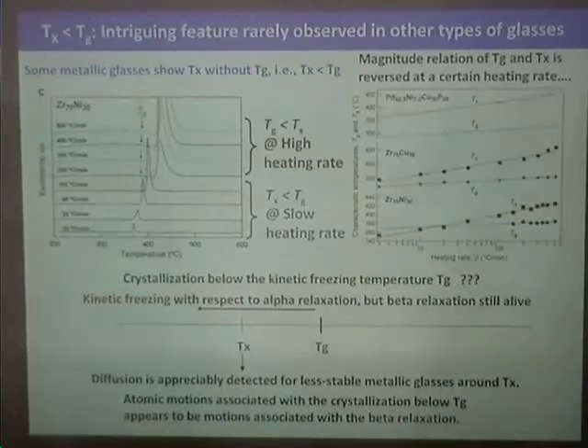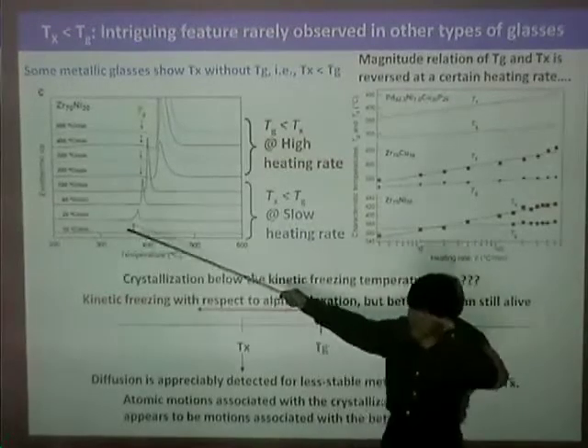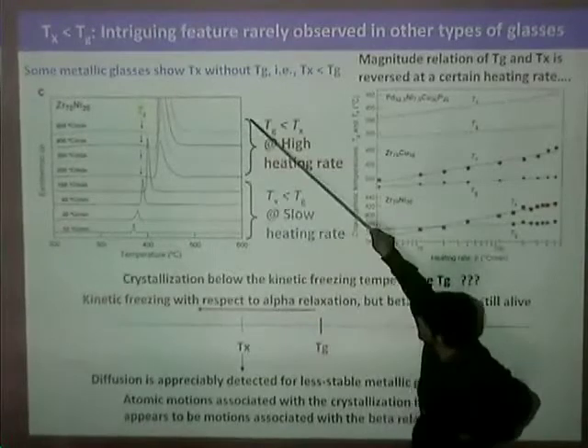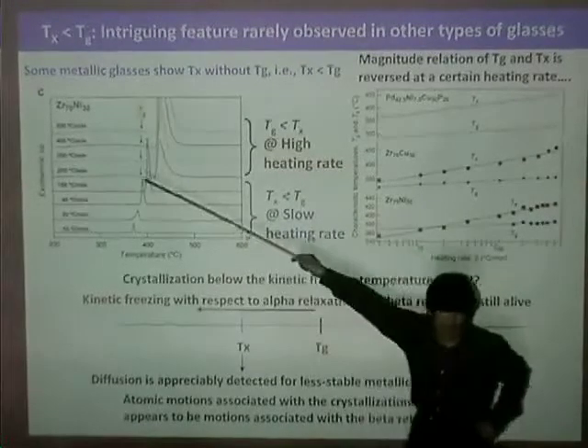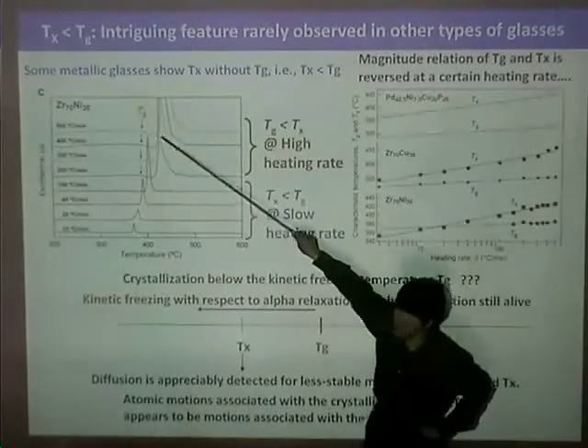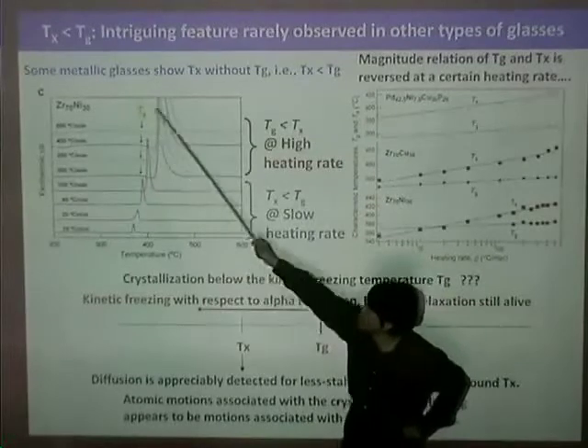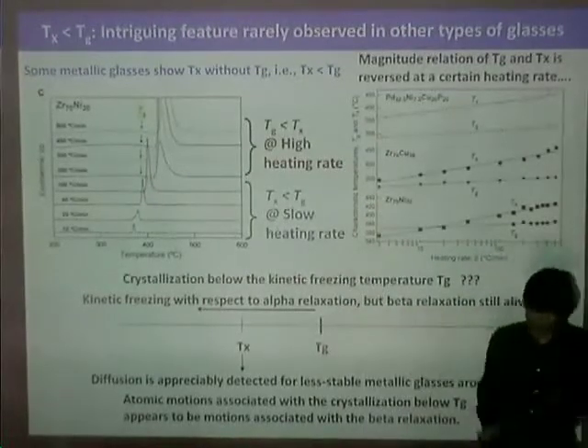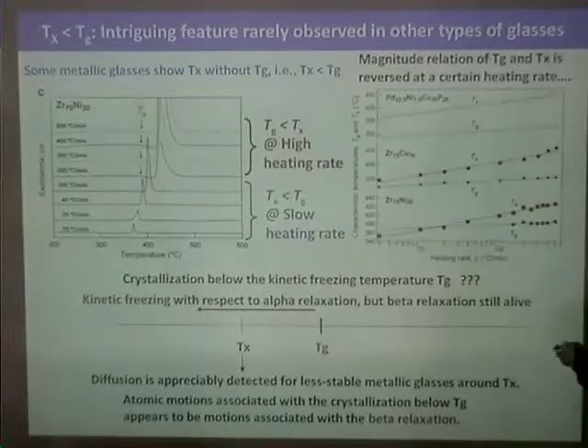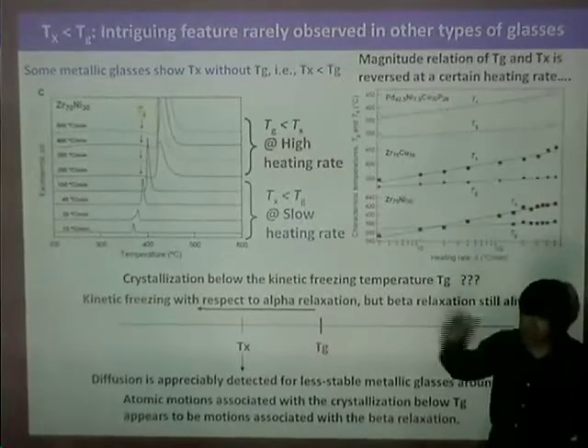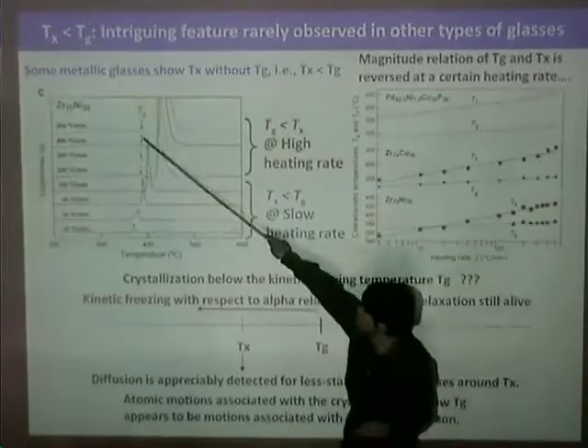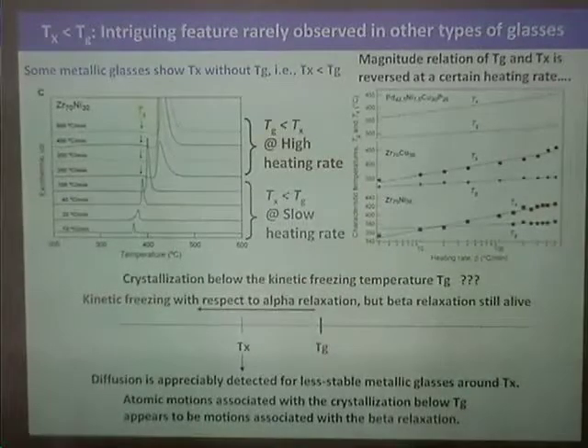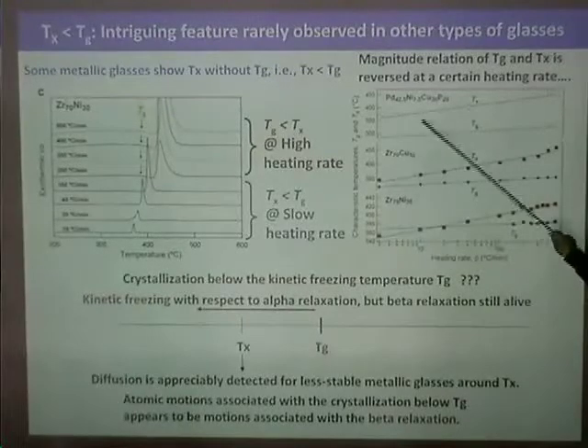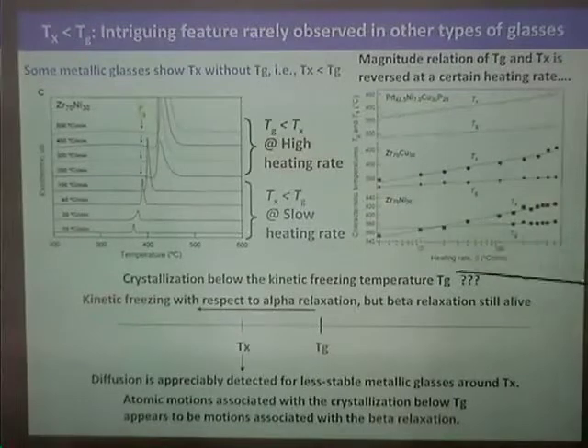But when the heating rate becomes higher, for example, 500 degrees centigrade per minute, we can observe the glass transition phenomena before the crystallization temperature. Because crystallization is caused by atomic jumps, when we rapidly heat the sample, the crystallization is very much retarded at high temperature. Therefore, the metallic glass transition can be observed. So this is Tg and Tx versus heating rate dependence.